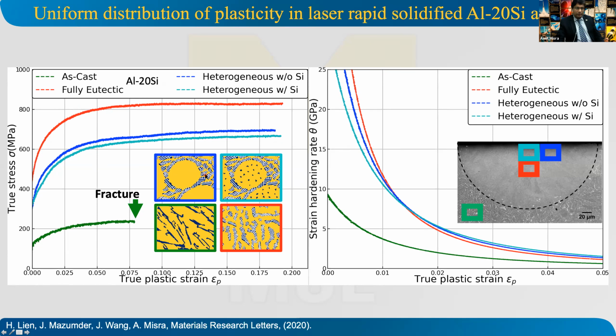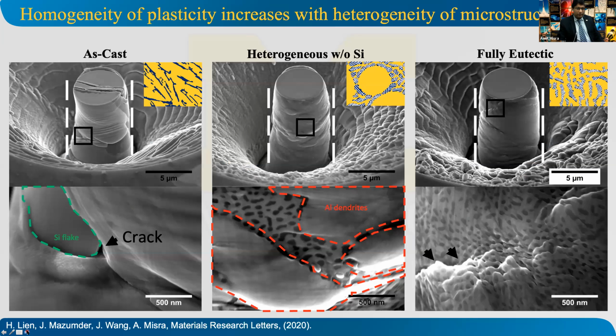The heterogeneous structures are a bit weaker because, as you would expect, the aluminum dendrites will have lower strength. But in compression, we are not able to tell the difference between the true plasticity. So we are doing tension tests to study that. So again, this is very promising, and this is just showing when you compare the behavior in compression, the as-cast,